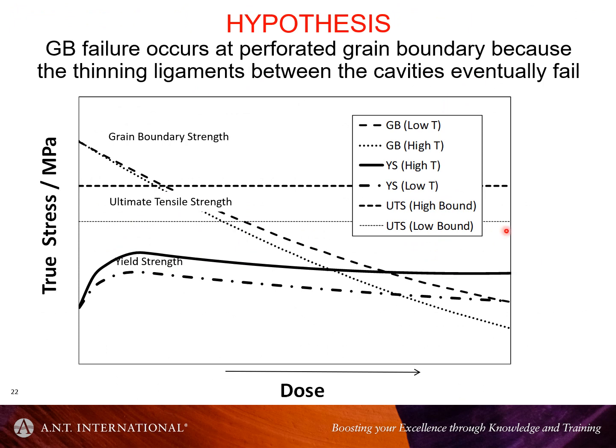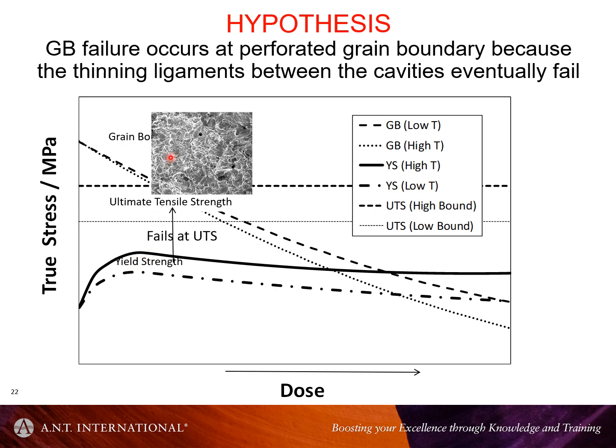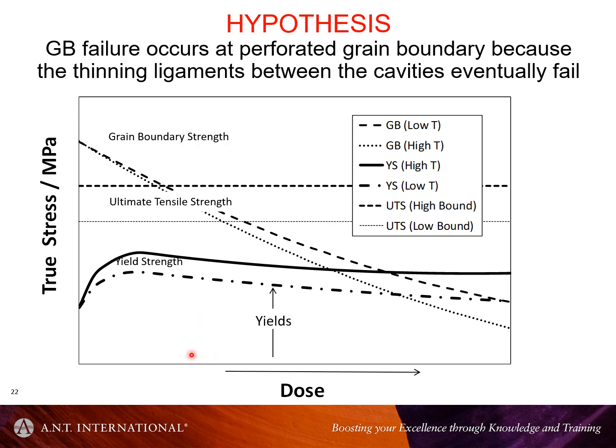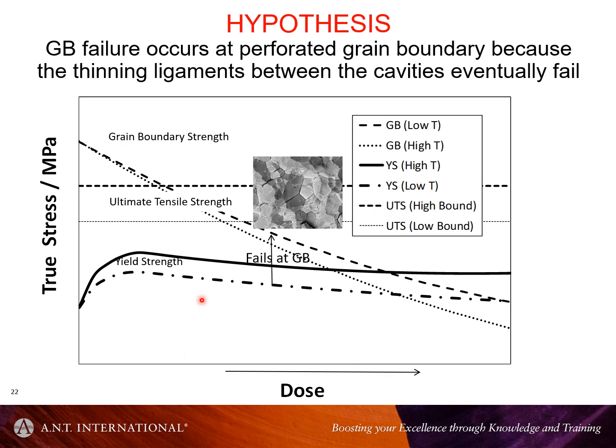So one can hypothesize about how things progress if we look at the true stress, imagining hypothetically in the spaces, and a dose without defining what that dose is. Normally at zero dose, you have a certain yield strength and a certain ultimate tensile strength, and the grain boundary strength typically is much higher than either of these. So when you deform, even at low doses when the material's hardened, it'll generally fail in a ductile manner, as it does in our spaces, even at low doses. But if you increase the dose, it might yield and then fail in a brittle manner.